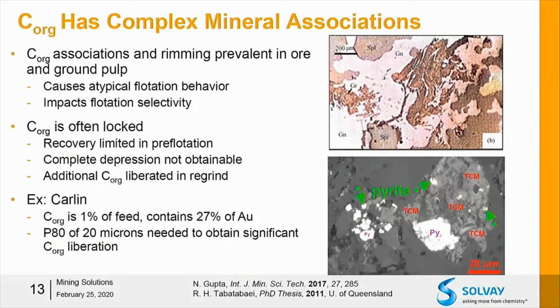And also, because of actual locking, complete depression is not necessarily achievable. It can be quite common to actually see carbon locked inside values. So even with a depressant in your rougher circuit, carbon can still report to the concentrate, and then it can actually be liberated in a regrind. So it can be important to actually add depressants at multiple stages throughout your circuit to manage that issue.